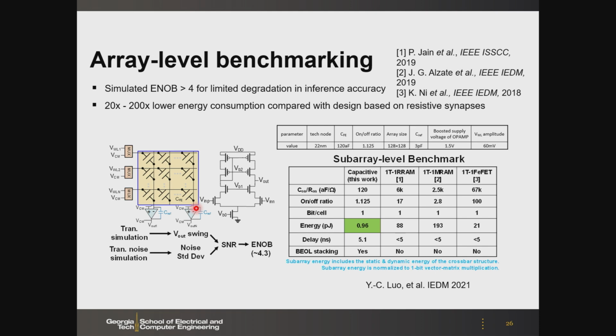kT over C is your thermal noise. So here we consider the thermal noise in the transient simulation, and then consider the swing of the dynamic range of the op-amp, and then this can get us this signal-to-noise ratio. And then in this case, the ENOB, the effective number of bits, is about 4, which is not ideal because here 128 by 128, at least you should get 7 bits, but here effectively you only get 4 bits.